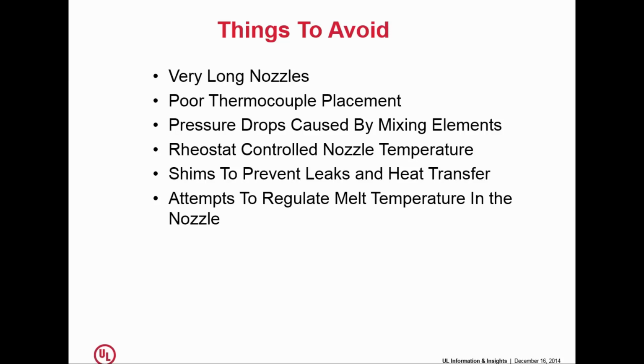Shims to prevent leakage and heat transfer, we talked about that, and attempts to regulate the melt temperature in the nozzle. Once the material is all the way up to the nozzle, you shouldn't be trying to change the temperature of the material at the last second. It should just be a pass-through to get into the mold from the front zone.